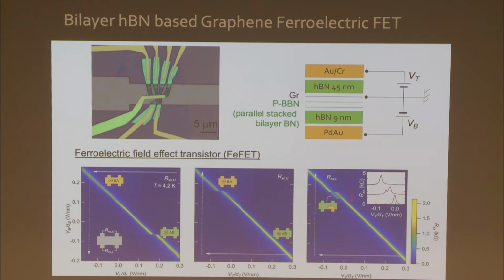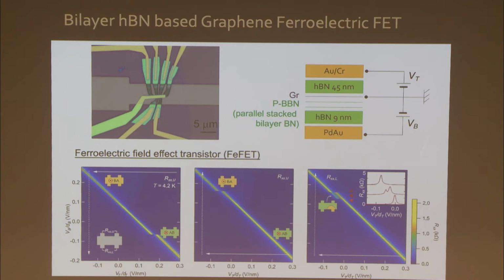In fact, we can do this continuously. Okay? And we can see how this resistance peak, as a function of back gate and top gate, switches abruptly when you go from the BA to AB type of stacking. If we now reverse the direction of your electric field, it switches abruptly at a different field. That's the ferroelectricity. Every now and then, we catch a domain wall zapping through our device, and we can see the bistable contributions from AB and BA at the same time.